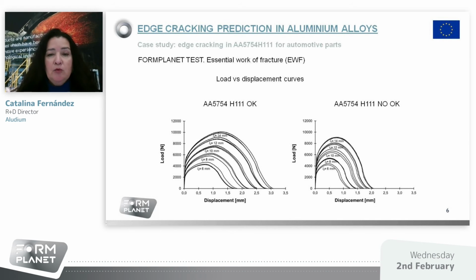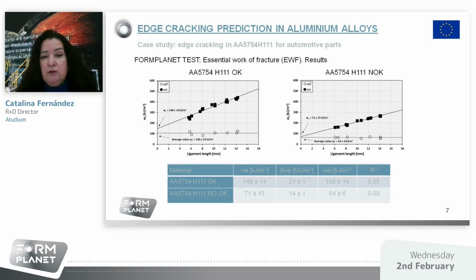Well, now the result of aluminum material. Here you can see the load versus the displacement curve for the OK left and no OK material. The area under each curve, the work of fracture, is much higher for OK than for no OK material. And when the specific total work of fracture is plotted against the ligament length, we can see a clear difference in values obtained for fracture toughness, 148 versus 71, in plastic work, 21 versus 14, as well as for the fracture toughness at crack initiation, 106 versus 64.